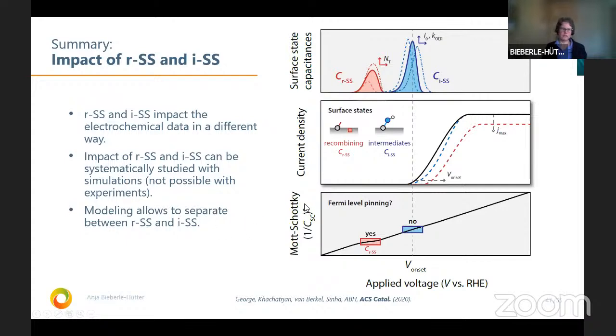Here is a summary of this surface state analysis. We see that these recombining surface states are at a different potential than the intermediate surface states, which gives us a measure for the experiments how this is. And we see how, for example, the current density changes. And this is what I said before with the Mott-Schottky, that here we get a Fermi level pinning, where this effect that we see in experiments and in the simulation is actually not a Fermi level pinning, but is related to a feedback loop of the serial resistance.